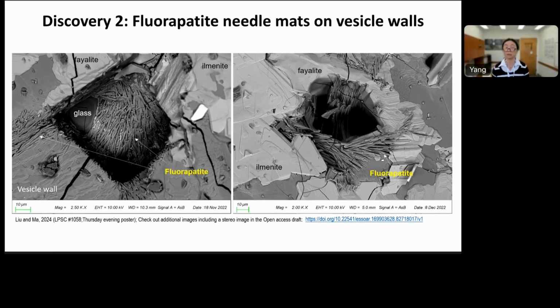But when you look at the images here, what you're seeing are, again, you're looking down the vesicle, and those are holes on the vesicle. So there are holes connecting the vesicle to the rock matrix. I always nickname the left-hand side as a hairball texture. So it's like a hairball down the drain. The right-hand side is different. It's more like fluoroapatite straws formed in cluster form.